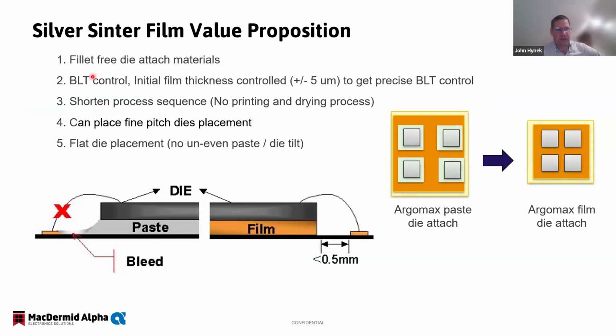Some of the big advantages are, we talked about what the drawbacks are using paste, and that's bleed out. Well, if you have bleed out, then all of a sudden you have areas where you can't place other components. You can see that here easily with film. We call this a fillet or a bleed out. So you don't have this with film. And what you can see here is you can actually achieve tighter packing densities. If you're going to have bleed out, you're going to have a no-go zone around that component that's not really required with the film process.